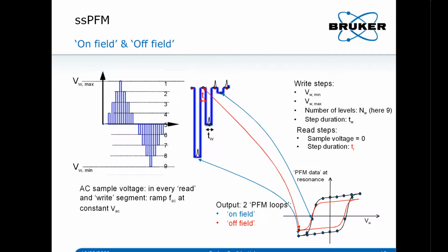This gives you the pulsed DC PFM, or the switching spectrum PFM as it was later named. The idea is actually quite simple. Instead of directly ramping the DC voltage as we do in hysteresis loop ramping, we separate it into several steps. At each step, I increase the DC a little bit. But after this step or pulse, I remove the DC and just apply the AC signal to read the piezo response. After the reading session, we do another writing session, or the on-field, as people usually call it, with a slightly higher DC. In this way, we can still finish the DC ramping, but now we can get both the on-field and off-field hysteresis loops.